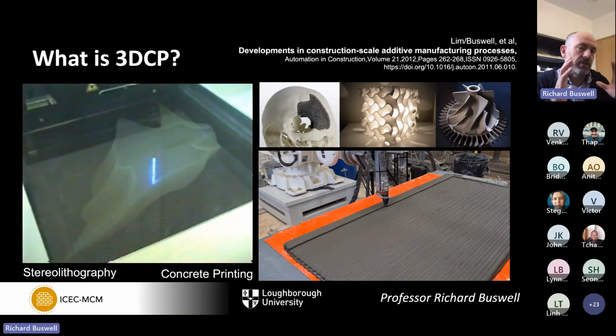So additive manufacturing, you work from a digital model, which you can create. Then you use software to break that model down into a series of machine instructions that guides the placement of material directly. So in the concrete printing image, which is the bottom right-hand corner, here we've got a wet mortar that's extruded into a nozzle, and then a robotic system or a gantry positioning system moves that nozzle around, positioning the material. That's built up in layers, and so you can then, a layer at a time, build up the facsimile, if you like, of your digital model.